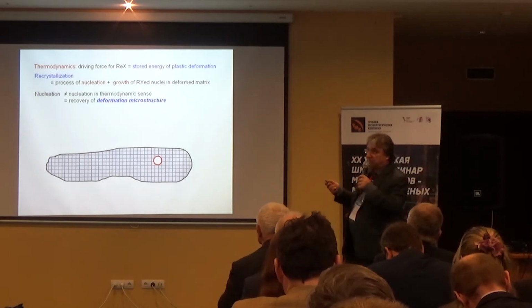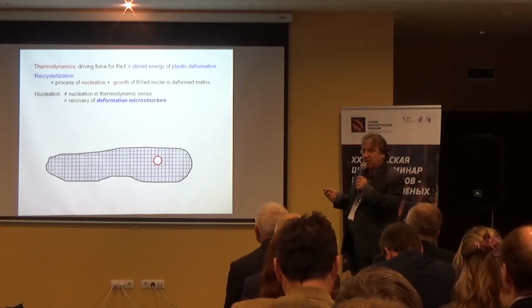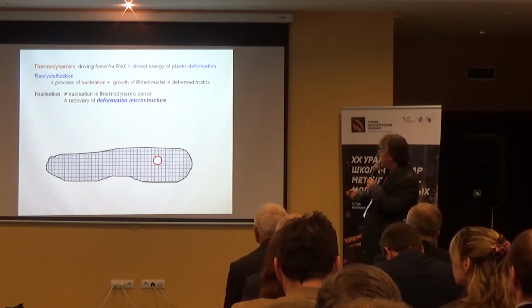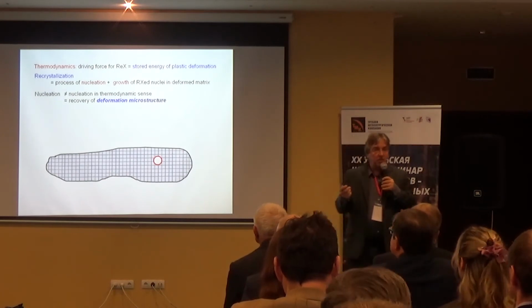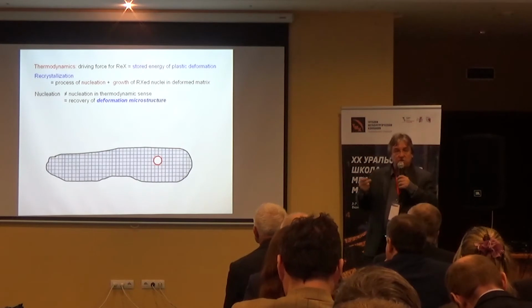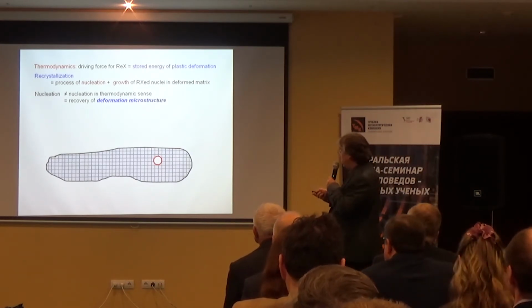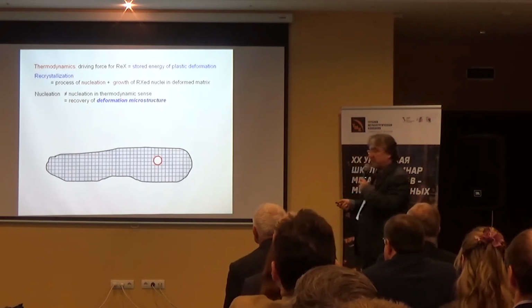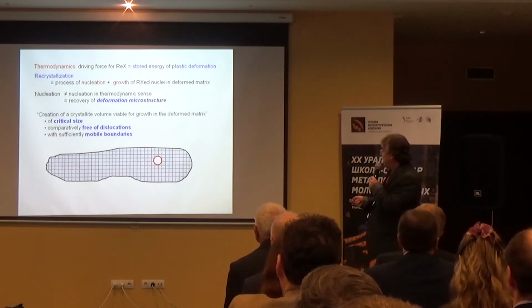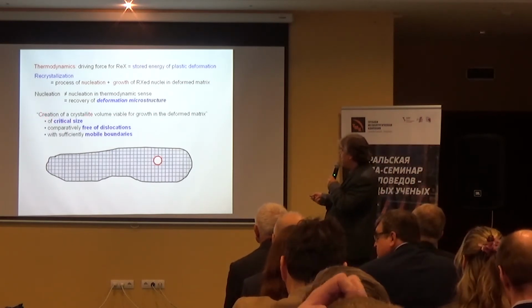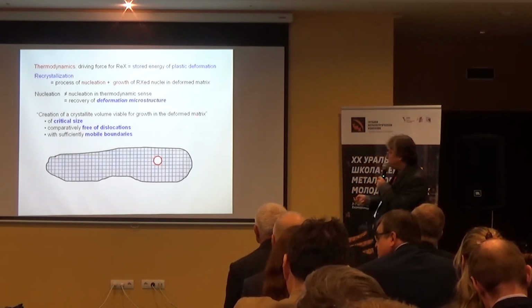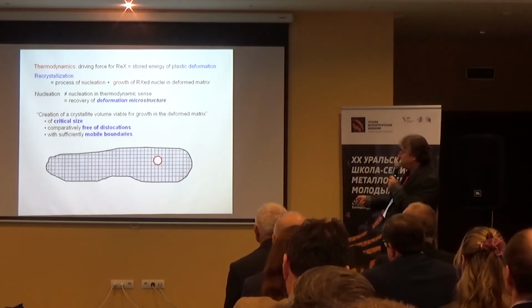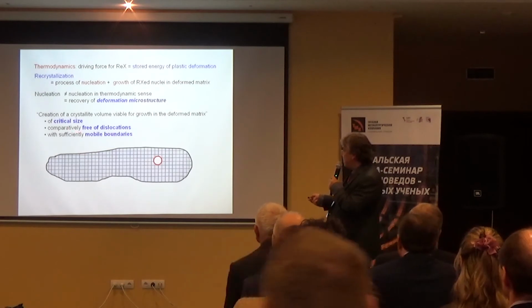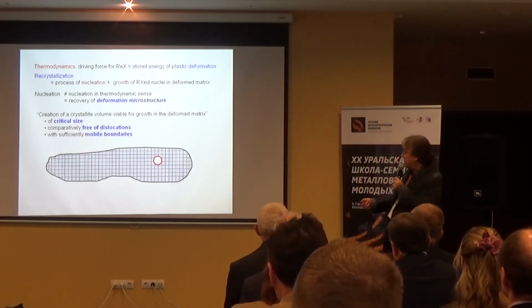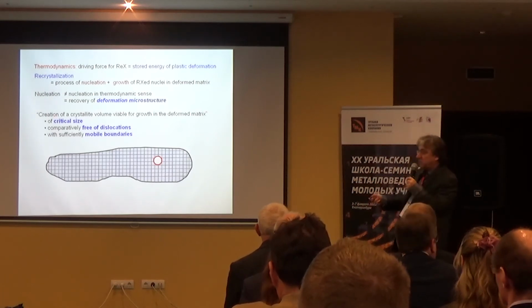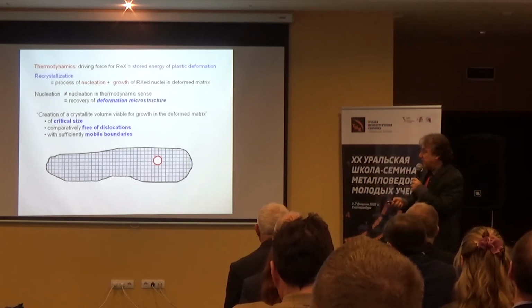matrix. Now, the word nucleation, we have to be careful here because in the context of recrystallization, nucleation is not the classical nucleation in the thermodynamic sense of the word, like when you have solidification or you have a phase transformation. Actually, what we mean with nucleation here in this context is the recovery of the deformed structure. So what it means is that you have to create a crystallized volume which is viable for growth in the deformed matrix. Therefore, it needs to be of a critical size, it needs to be free of dislocations, and it needs to have sufficiently mobile boundaries. So these are the three conditions that must be fulfilled to have a recrystallization nucleus.